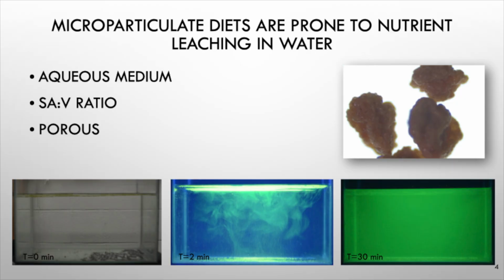So the current microparticle diets are highly prone to nutrient leaching due to their high surface area to volume ratios caused by their small size and porosity. The images along the bottom show the resultant rapid nutrient leaching of sodium fluorescein, which we included into our house-made diets. And sodium fluorescein acts as a water-soluble nutrient proxy. As you can see at the zero time point, there's very little nutrient leaching. And then by 2 minutes, there's already quite a bit. And then this is the 30 minutes.